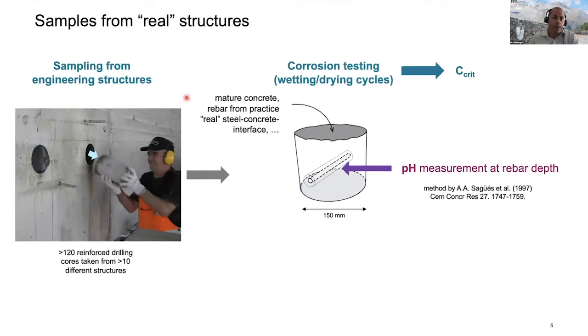So what we did is we took samples from engineering structures. You can see here reinforced concrete cores. These cores have a diameter of 150 millimeter. They contain a piece of reinforcing steel, which at the time of sampling was not corroding. And then those samples were exposed to cyclic wetting and drying in chloride solution in the laboratory until corrosion initiated, which allowed us to determine the chloride threshold value or critical chloride content, however it is called, here abbreviated with C-crit. At that point in time, we also measured the pH of the concrete at the depth of the rebar by using a method that Alberto Sagüés and colleagues proposed in the 90s, which essentially consists in drilling a small hole into the concrete, adding an electrolyte, for instance distilled water, and then after a certain equilibration time, measuring the pH in that liquid.